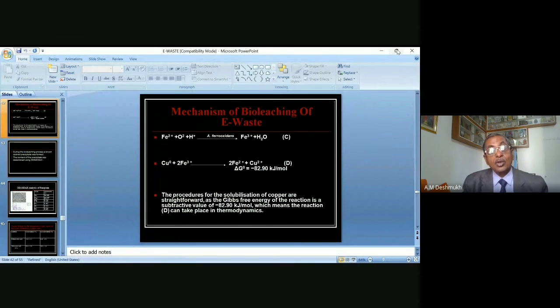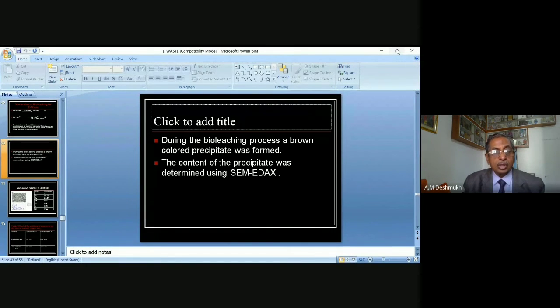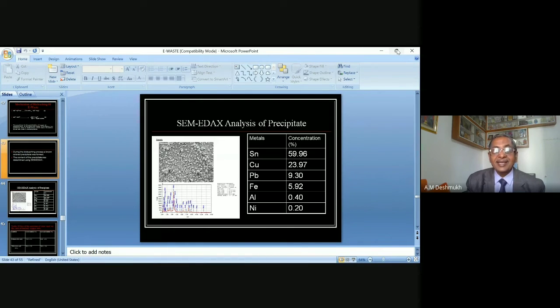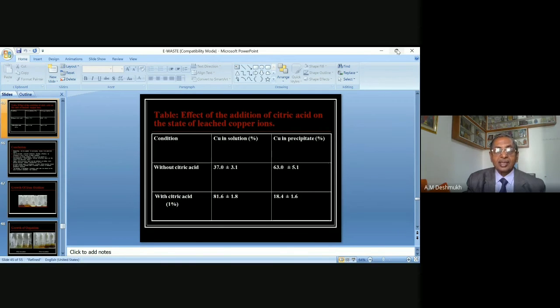That is the beauty of the biotechnological method. These microorganisms are not asking salary from us. They are happy because they are getting an energy source. And without any charge, without any cost, without any labor cost, they will convert ferrous iron into ferric iron. So during the bioleaching process, a brown colored precipitate was formed and the content was determined by the EDAX method. Here, the EDAX analysis was carried out and concentrations of different metals in our leachate were detected. And citric acid we found is helpful during the process.